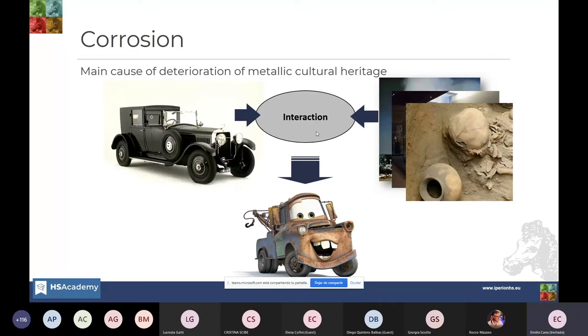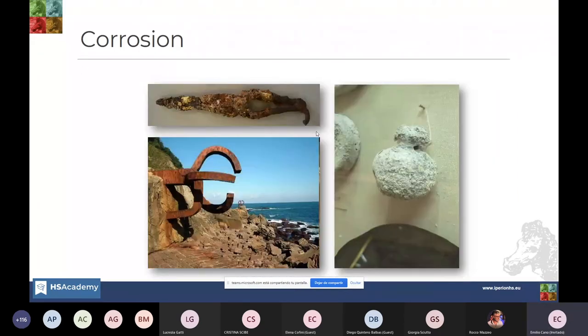Well, these are some examples that I have taken of different environments: a sample of an archaeological artifact which has corroded during burial. We have this Peine del Viento, which, as you can see, is heavily corroded because it's exposed to the seaside. Or some other artifacts like this one, which is a lead weight exposed in a museum, which is also heavily corroded by the vapors released by the materials used in these display cases.